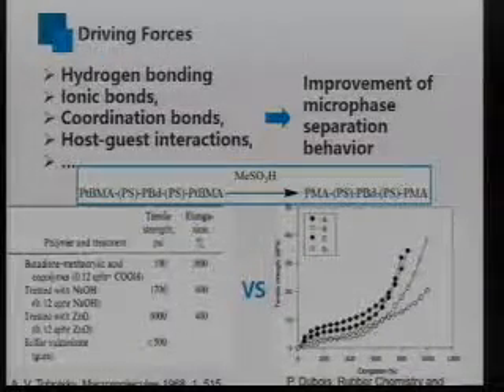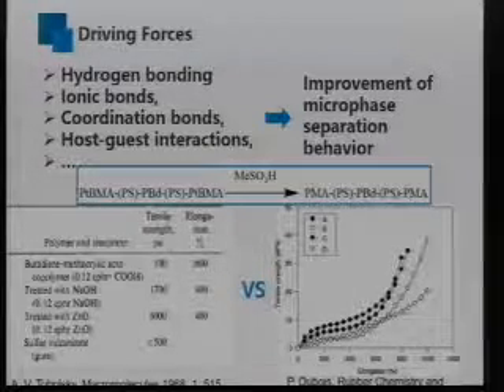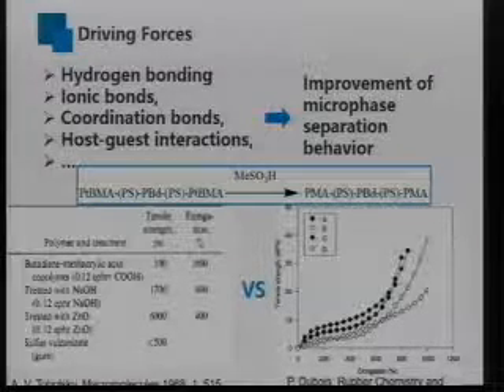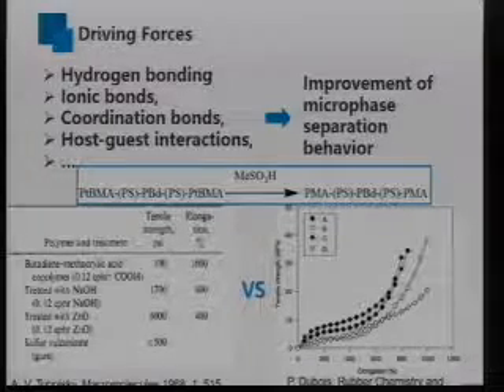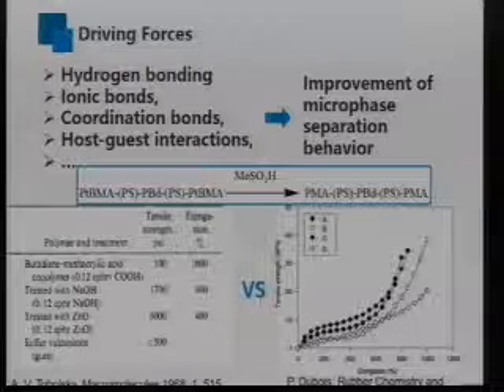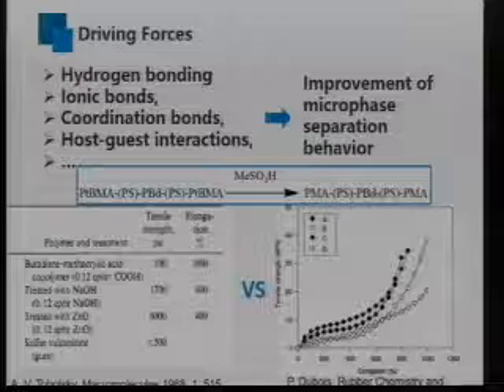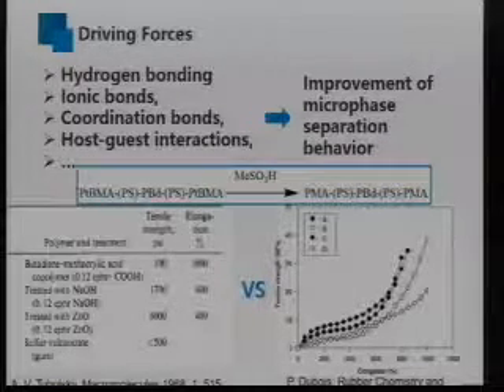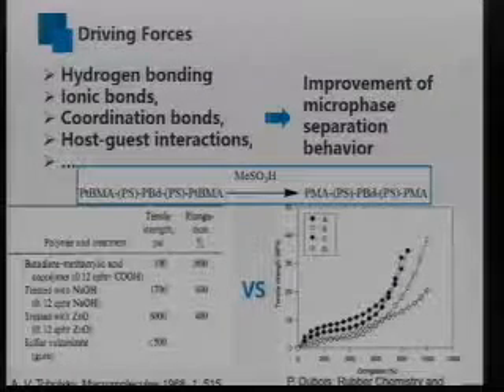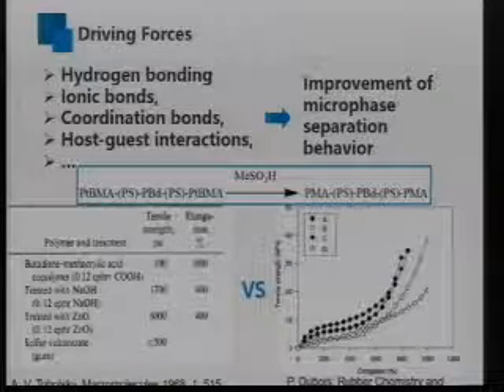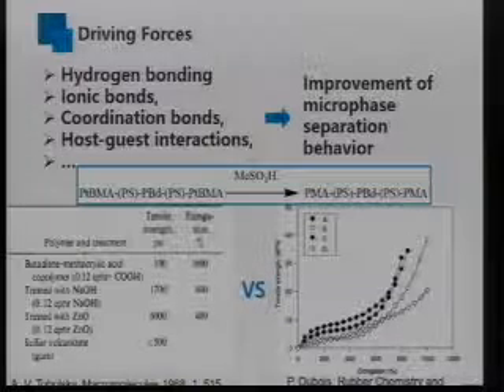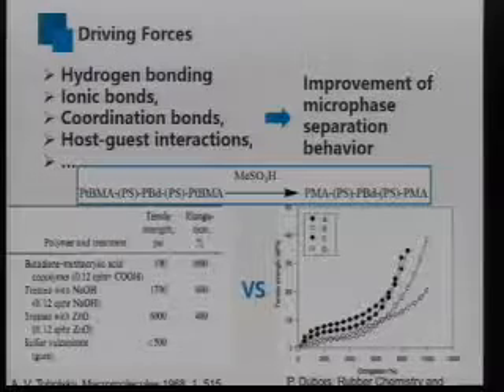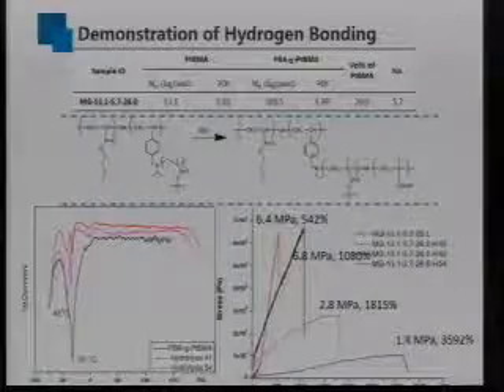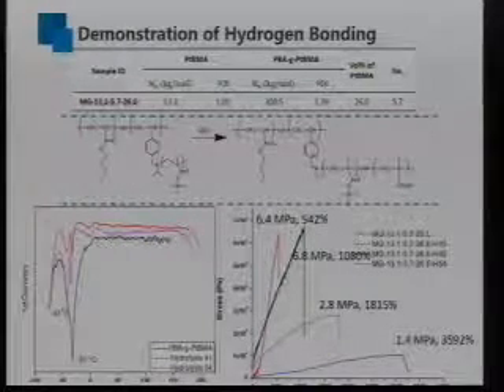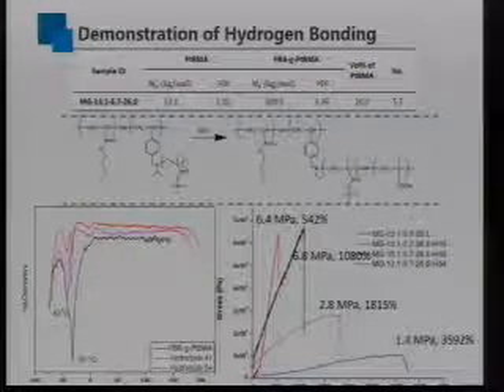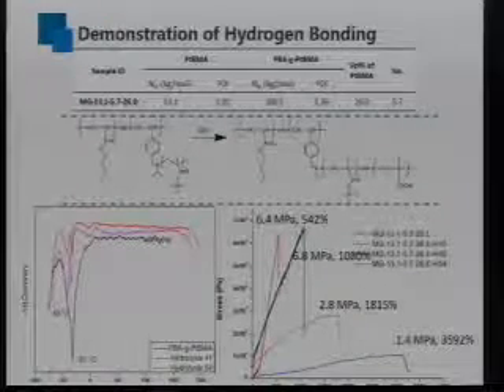Further improvement of the mechanical strength of the material was pursued by the introduction of extra driving forces, such as hydrogen bonding, ionic bonds, coordination bonds, or host-guest interactions, which can be used to improve the microphase separation behavior of the material. However, different results were reported before. For thermoplastic block copolymers, they reported that the introduction of hydrogen bonding, ionic bonds, and coordination bonds can lead to an increase of the tensile strength, but with a decrease of the elongation. In another work, with the introduction of hydrogen bonding, the mechanical strength decreased, but the elongation increased. As a demonstration of hydrogen bonding, we synthesized a graft copolymer of polybutyl acrylate-graft-poly(t-butyl methacrylate), using the same strategy as for the graft copolymer of PBA-graft-PMMA.